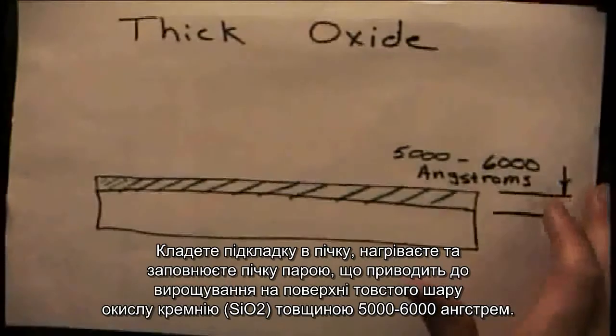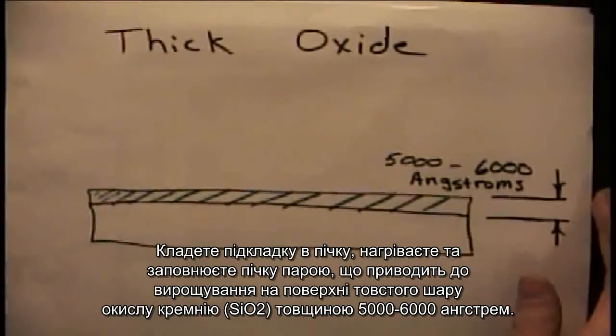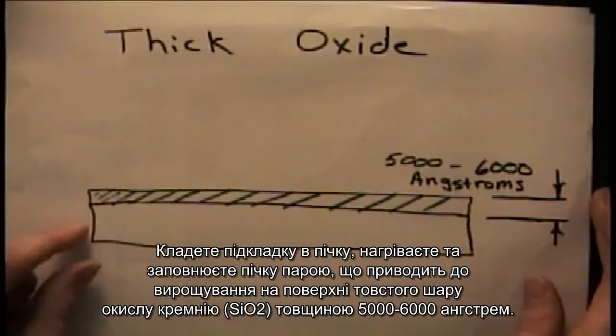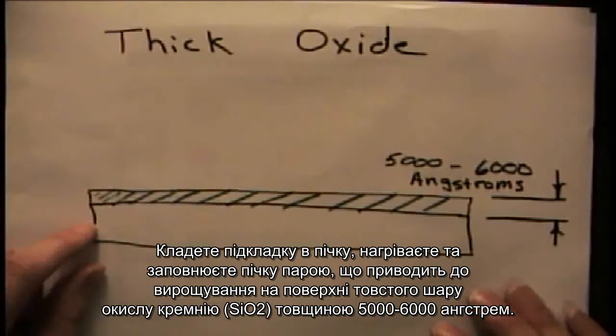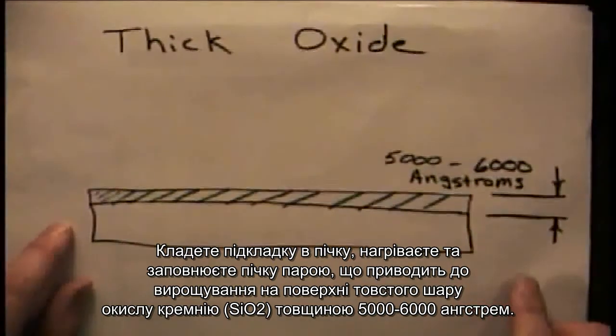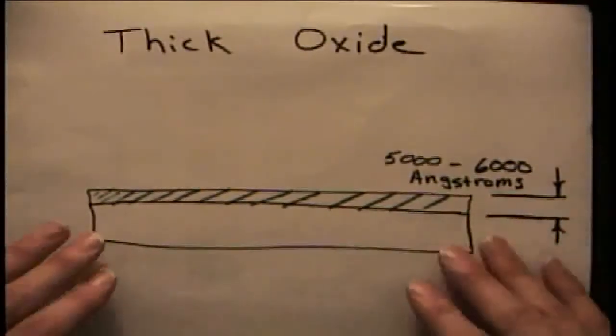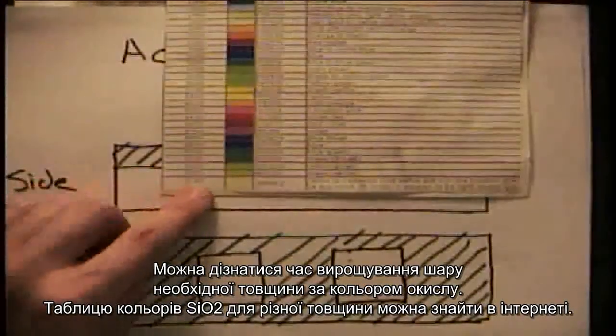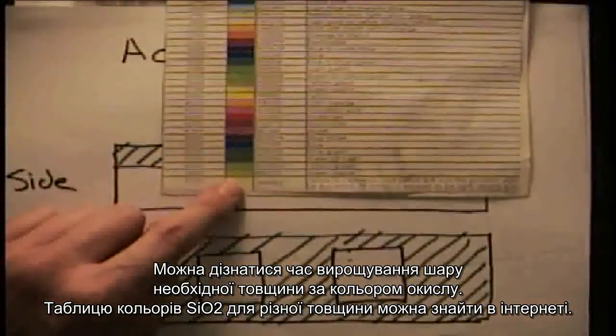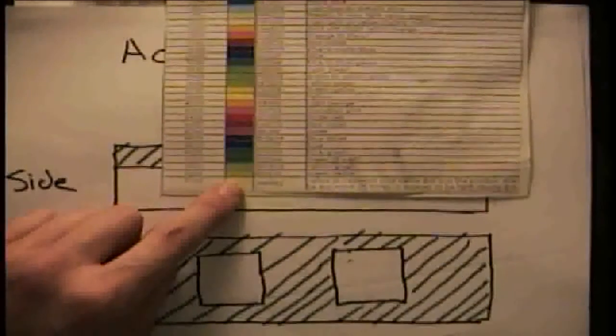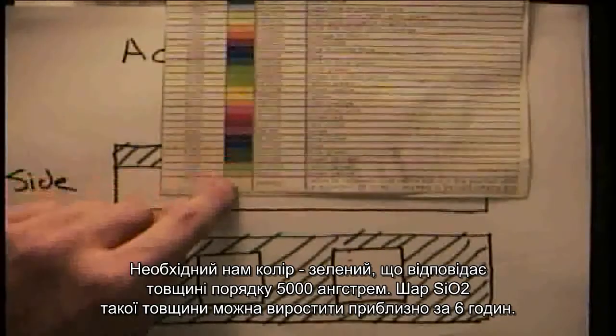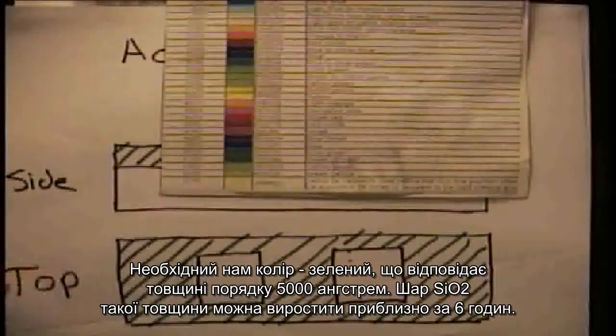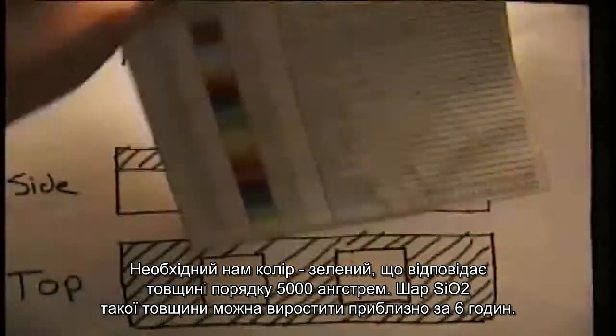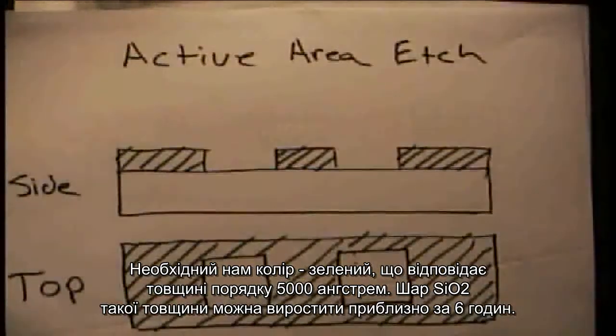You put it into your kiln or your furnace, and you pump steam into the furnace, and you're going to grow a thick oxide layer that is 5,000 to 6,000 angstroms thick on the top of the wafer. You can tell when you've reached that thickness by a color chart. You can find this color chart online in multiple places. But you're going to be shooting for a green color, and it's going to take about 6 hours to grow that on top of the wafer.